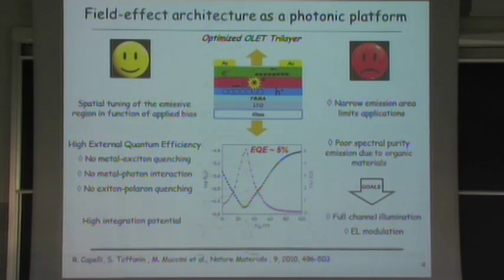We are driven by different benefits present in the field effect architecture, like the spatial tuning of the emissive region as a function of the applied bias that leads to high external quantum efficiency, because we have no metal exciton quenching, no metal photon interaction, and also no exciton polaron quenching. Furthermore, the integration potential is very high in this optoelectronic device. Unfortunately, there are several drawbacks, like the narrow emission area, which limits the applications, and the poor spectral purity, which we tried to solve.